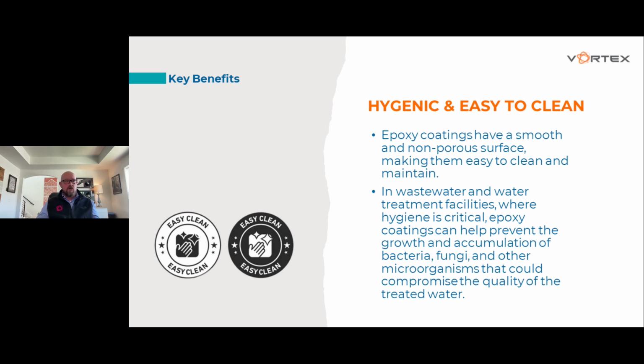And a lot of times, if you just have bare concrete, you will get a tuberculation on that substrate itself that's very difficult to remove. When you're using epoxies, you create this non-porous substrate that doesn't allow for things to hang on to it. It's almost a defouling property that's inherent. And so with that defouling property on our epoxies, we're able to eliminate the adhesion of other corrosives onto the surface. And if we do get some corrosives onto the surface, we're able to easily clean that using simple water pressure, really, to remove that from the epoxy itself.